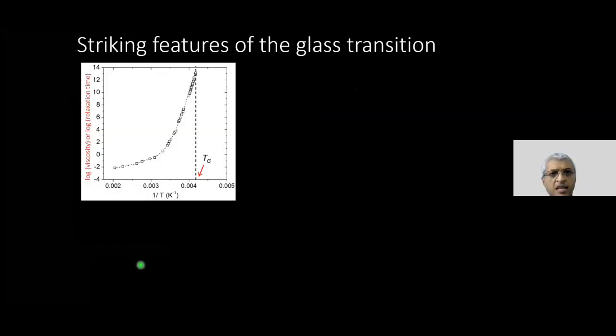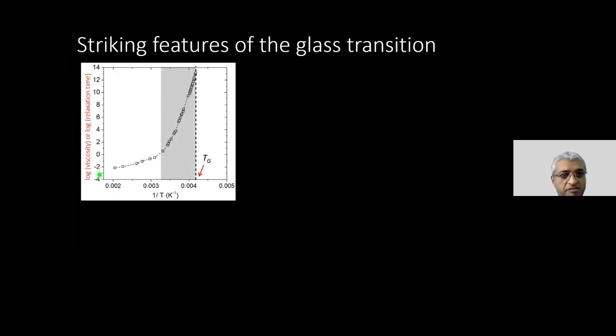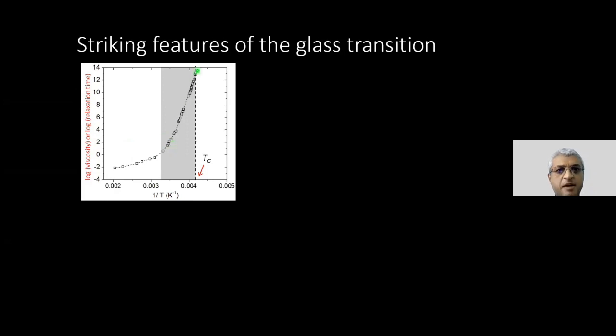Now, what's spectacular about the glass transition is that instead of looking at just the volume or the enthalpy, if you were to look at, say, the viscosity or the relaxation time, by relaxation time, I just mean the time it takes for a particle to move its own diameter, and plot that quantity as you start cooling the liquid, what you essentially find is that in this very narrow window, just about 60 Kelvin, you are changing the property of the fluid, either the viscosity or the relaxation time, by about 14 orders of magnitude. So this is very spectacular in that sense.